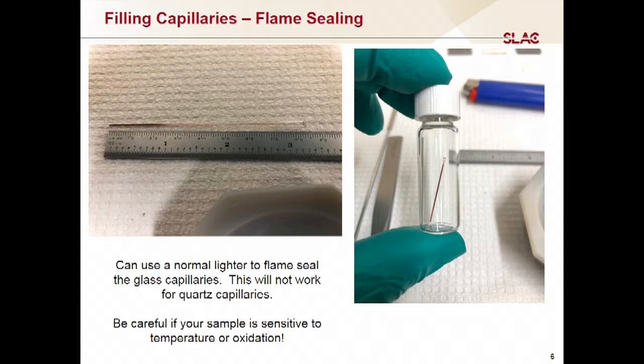If you have a sample that is very sensitive to temperature, you want to be very careful doing this, or you don't want to flame seal, because the sample doesn't necessarily get very warm when you do this, but it may get a little bit hot. The other thing is, if you're very sensitive to temperature or oxidation, if I'm flame sealing here away from the powder bed, I still have all of this powder that's kind of coated on the inside wall of the capillary. And if I get that very hot, it may change phase.